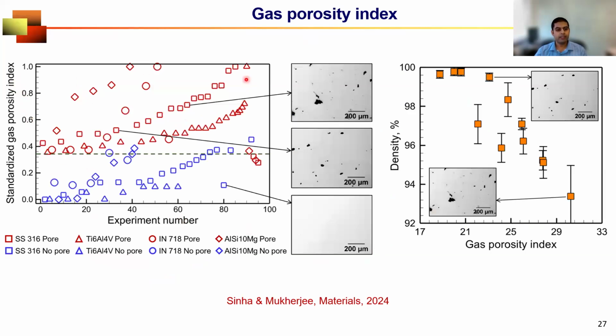Depending on the index, we can classify the cases where we see porosities and the cases where we do not see porosity. We have about 100 experimental cases for 4 different commonly used materials, and these 100 data points are collected from the literature, different papers that are available. And we see that no matter what process parameters we are using, a simple time ratio can delineate the defect-free cases from the defective cases. And when we have defects, the index is also useful to represent the density, or 1 minus porosity, very accurately. So this is another great example where a simple temperature field and molten pool dimension calculation can give you very important insight to solve very important problems.